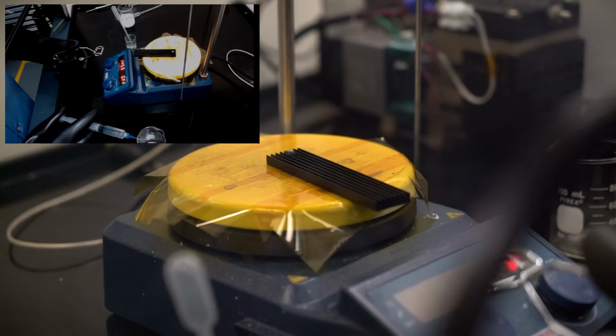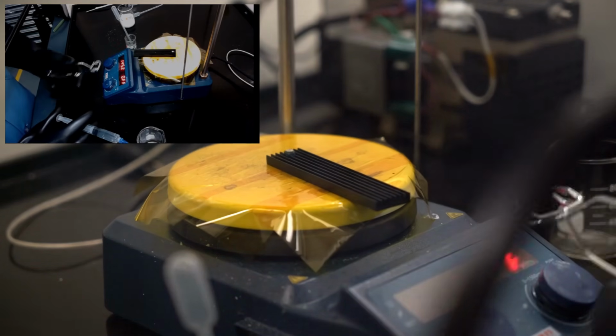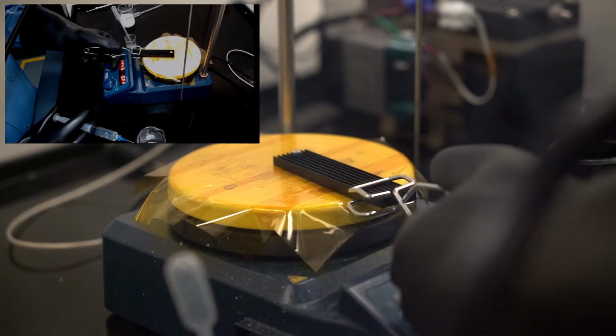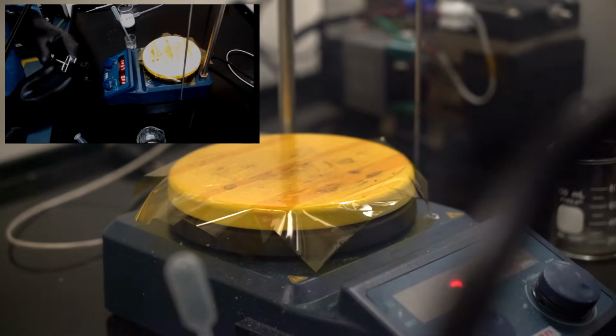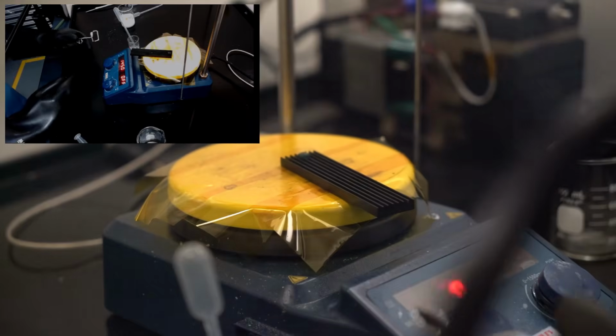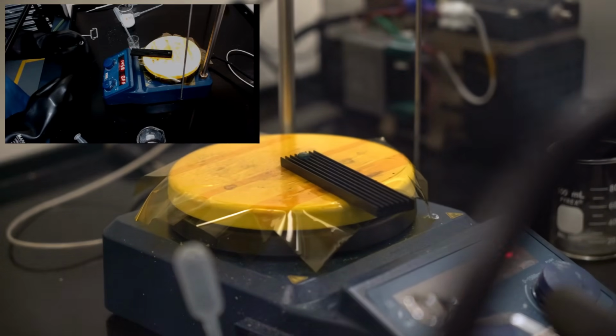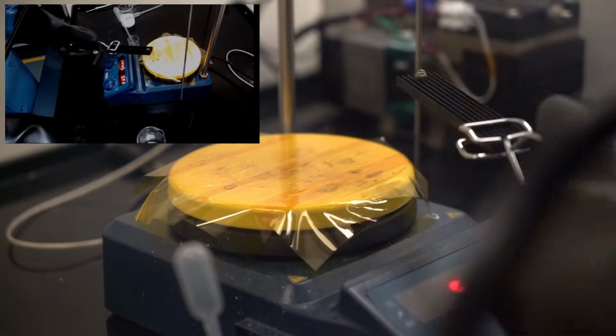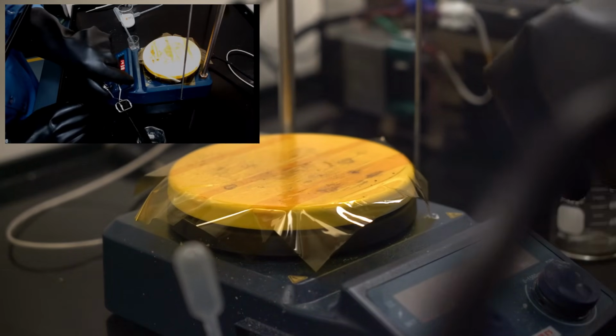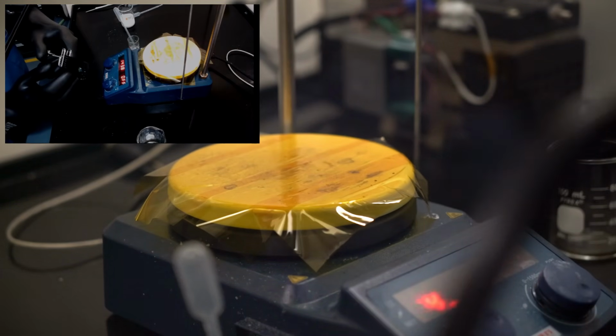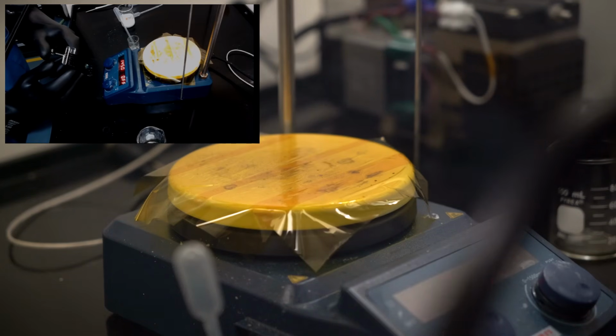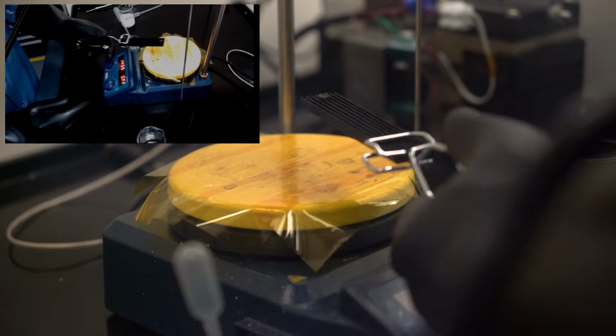This was a little tricky because I was able to use an aqueous clean on the heatsink to get all of the sulfuric acid residue off of it, but there was still some in the sample. The nitric cleans off nicely with acetone. The sulfuric is less soluble and tends to kind of leave residue on things that requires a lot of water to get off, and that's not compatible with an in-process clean with this process, since it'll damage the passivation layer on the bond wires, which are now exposed.